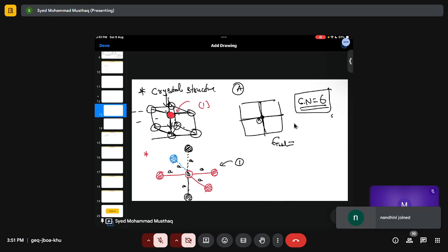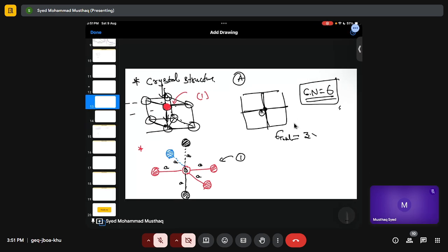So the total energy of this atom will be coordination number times the bond energy between two atoms, right? So that will be equal to delta H, the enthalpy of bond breaking or bond formation, divided by 2, because I am talking about one atom.